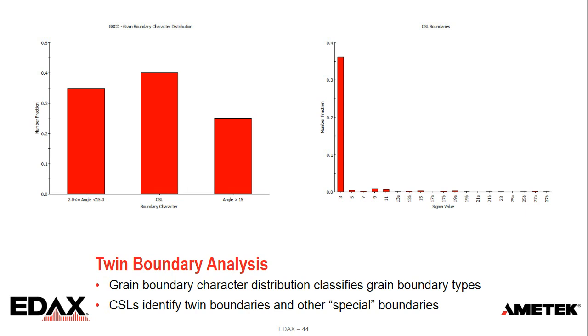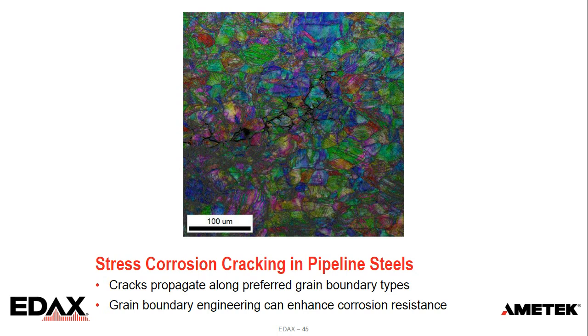This can be important for something like stress corrosion cracking. This is in a pipeline steel. This is an example of a crack going through a piece of this steel. The cracks tend to propagate along specific grain boundary types. They generally try to avoid going through a twin boundary. So there's work done called grain boundary engineering, where materials are subjected to different deformation and heat treating cycles to increase the number of twin boundaries and help enhance the corrosion resistance.